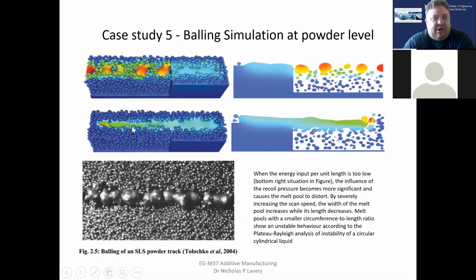It has sufficient power to melt a track, and you can see a relatively straight track forming on top of the powder, whereas on the top one, it's been moving too fast, there isn't quite enough laser power, and you get this balling behind the track. That's what happens below, when it's not completely fusing properly.